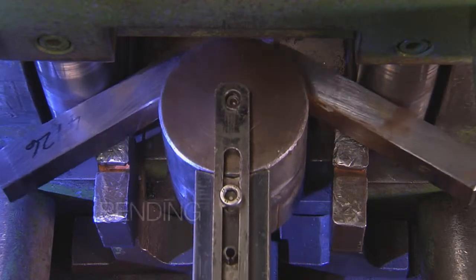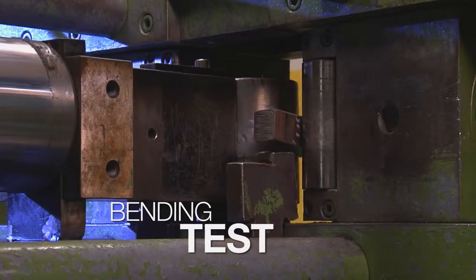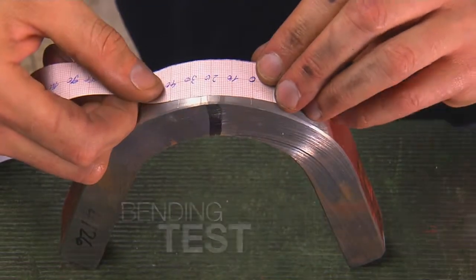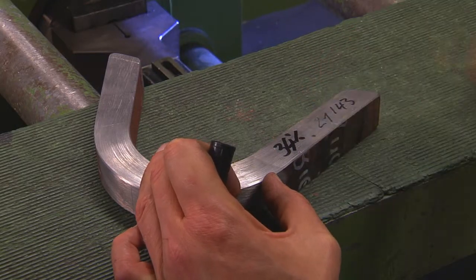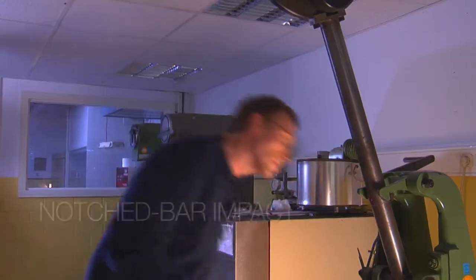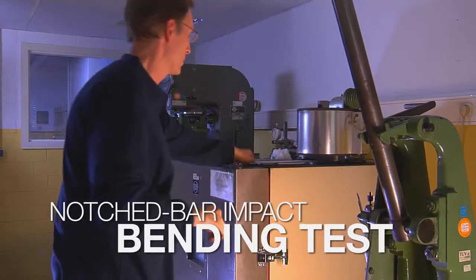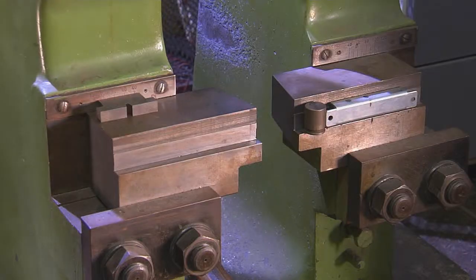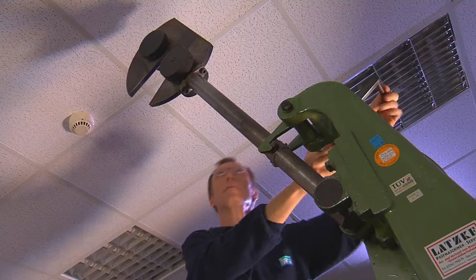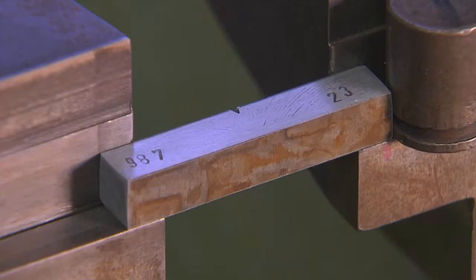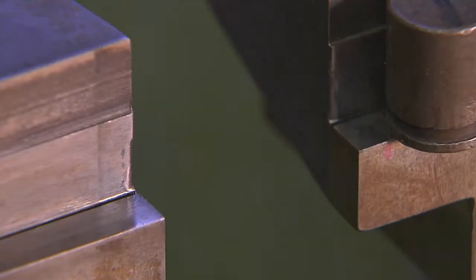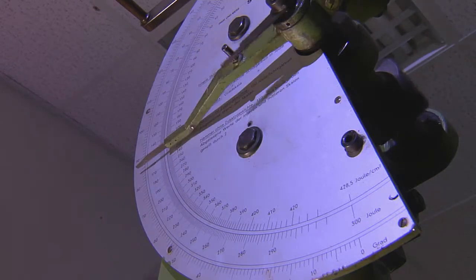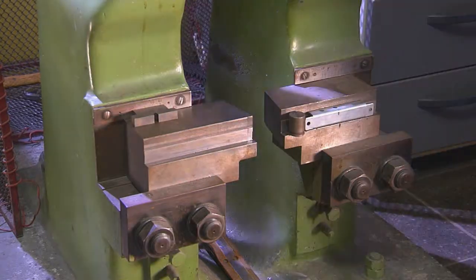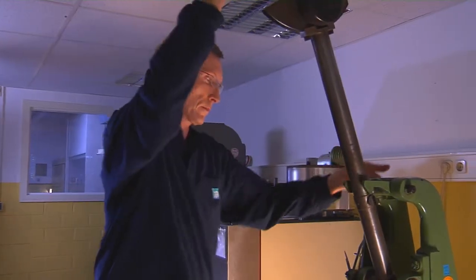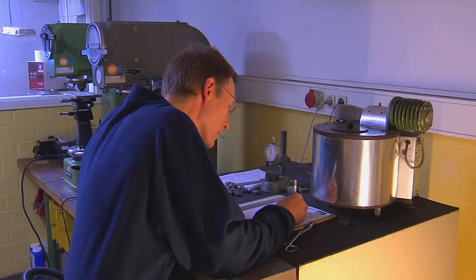The bending test shows the extent of plastic deformation and the quality of the weld seam. The notched bar impact bending test examines the toughness characteristics involved. Test condition: material temperature precisely minus 20 degrees Celsius. The notched bar impact hammer strikes the unilaterally notched workpiece at high speed. The energy that is absorbed while the sample is being shattered enables conclusions to be drawn about its toughness.